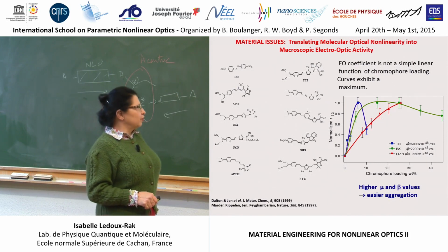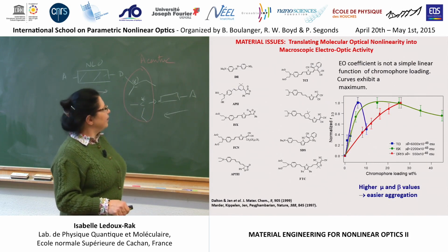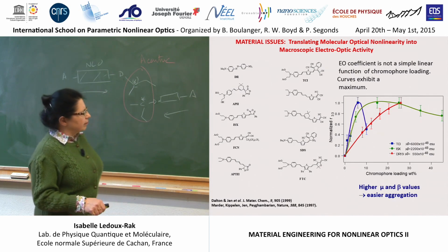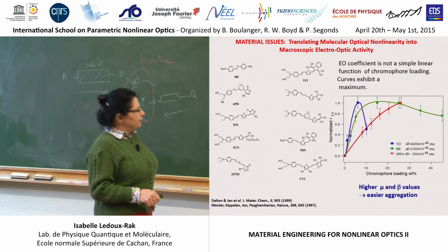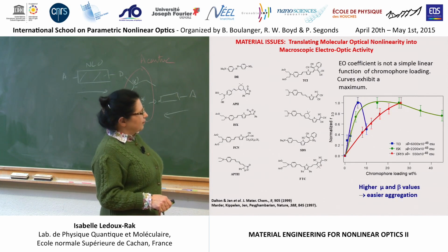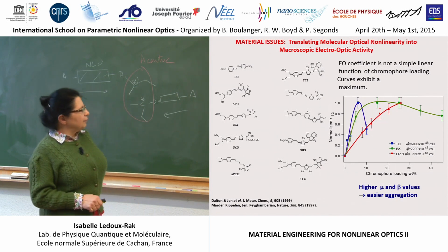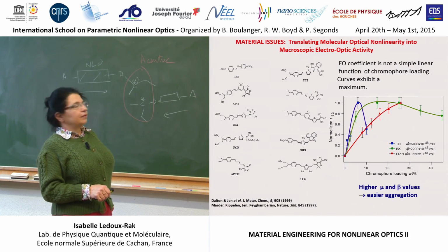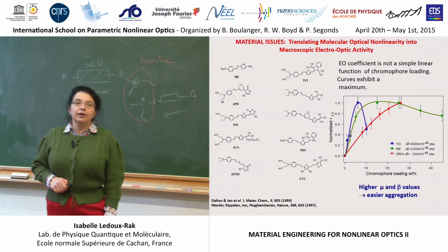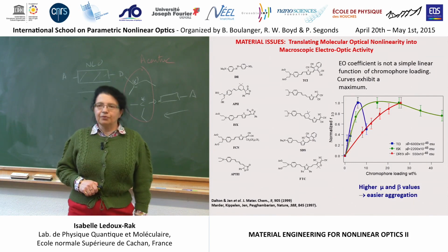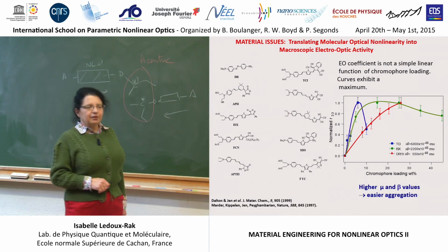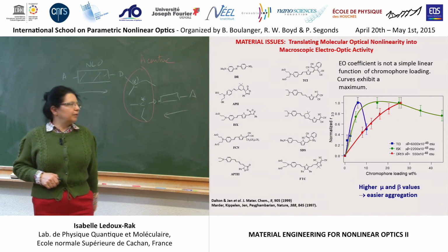But by taking much more efficient molecules, this one, ISX, in green, these molecules are almost 50 times more efficient than the dispersed red one. And we found the problem that after 10%, the response is maximum and even decreases when increasing the concentration. Because for highly concentrated systems, molecules are too close to each other and antiparallel dipolar coupling dominates.